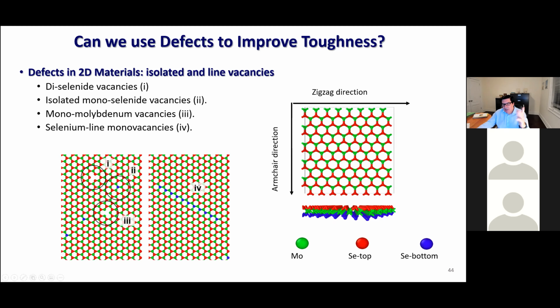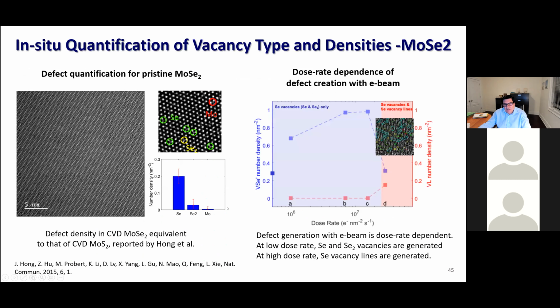And one way that you can see in the literature of graphene is using vacancies, using defects. There are a number of vacancies that you can form: single vacancies, clusters of vacancies, lines of vacancies. I will show you some results using the parameterized force field. But before I do that, I want to show what are experimentally reasonable densities and types of vacancies. So we did again electron dosage experiments and showed that if you increase the dose rate, you will increase the number of single vacancies.